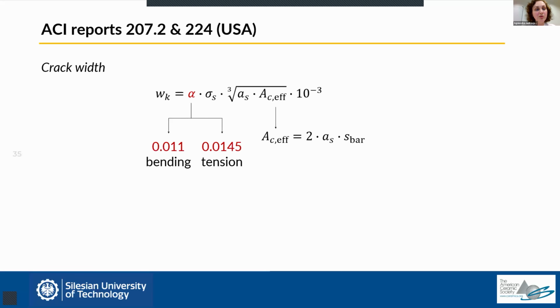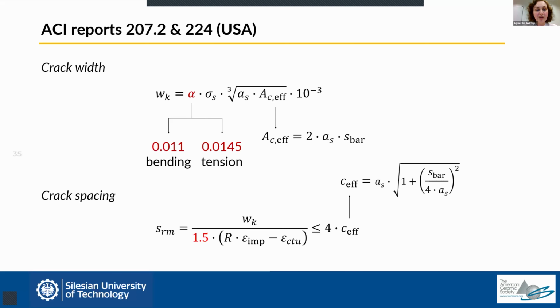The difference between the European approach and the American approach is that in the European approach, first we calculate the crack spacing and then the resulting crack width. And in the American approach, it is the other way around. First we calculate the crack width, and from that we can calculate the crack spacing. But if you remember, or if you watch this lecture once again later, you can make a direct comparison between this approach and the European approach, and you see that the formula is exactly the same. So the correlation between crack width and crack spacing is exactly the same as in the approach of Eurocode. The only difference is in this factor, which converts mean crack width to maximum crack width, because in the American approach this is 1.5 and in the European approach it is 1.7.